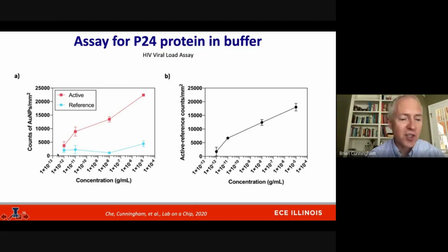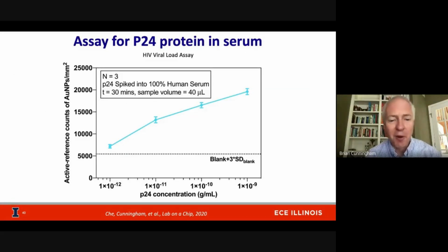So here I'm just showing you the nanoparticle counts as a function of P24 concentration for the reference region and for the active region. And then we can just subtract one from the other to have the final referenced count, or density, of captured gold nanoparticles. We did this first in buffer, and then more recently we did it for P24 protein spiked into human serum, 100% human serum, so kind of a viscous material, but again using the same 40 microliters in 30 minutes, where our limit of detection was around 1 picogram per ml.